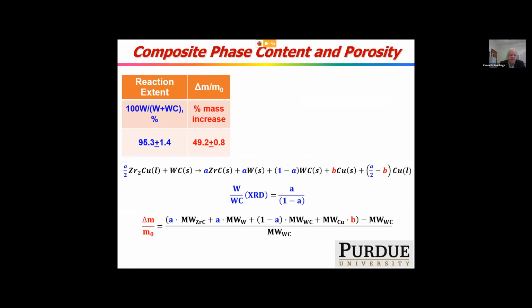And so what you see on the left there is the typical extent of reaction. Something like 95% is typical for us. The reaction below is the overall reaction. Zirconium copper liquid goes in, reacts with the tungsten carbide, it forms ZrC, it forms tungsten. We may have some residual tungsten carbide that didn't react. We may have some residual copper that didn't leave, a solid, and the copper that left.